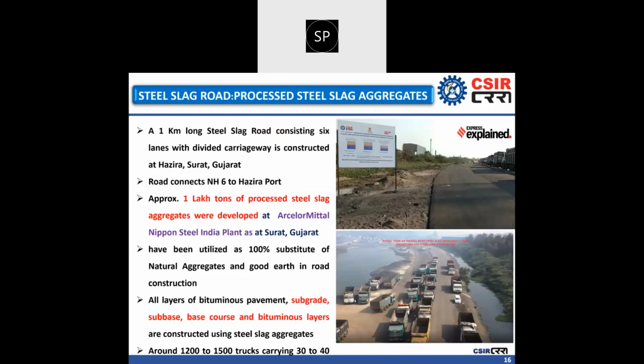Now, this is the glimpse of the road which we have constructed at Hazira, Surat using 100% processed steel slag aggregate. It's a 1 kilometer long 6-lane road which connects NH6 to Hazira port. Around 1200 to 1500 commercial vehicles per day are moving on this road, carrying 30 to 40 ton payload, and all the layers of the pavement, from subgrade to bituminous layer, are constructed using processed steel slag aggregate. There is no natural aggregate inside this road. Besides that, the road median, road shoulders and side drain too are built through the processed steel slag.